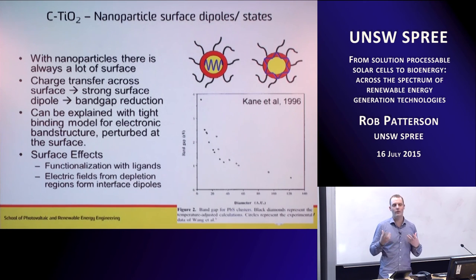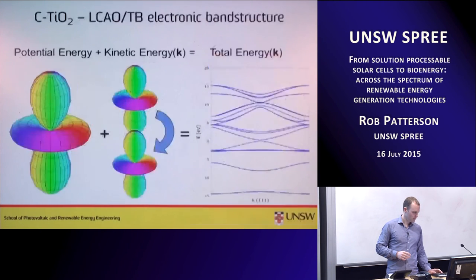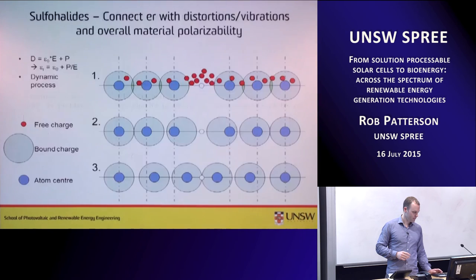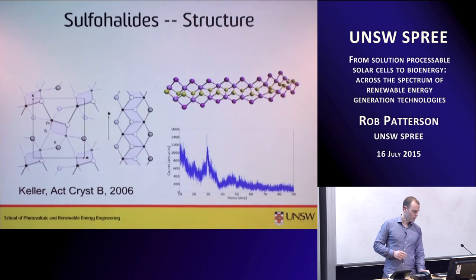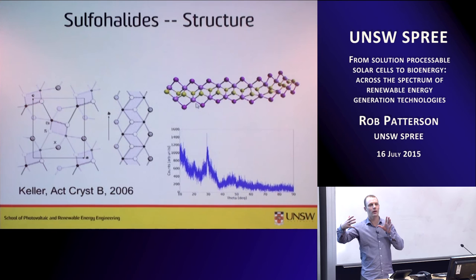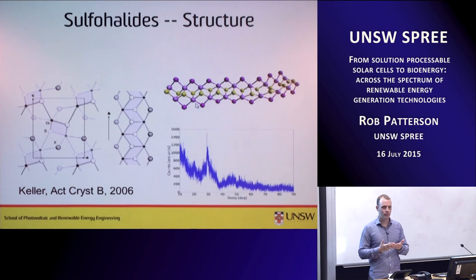The main reason, I think, is just because we have iodine on the surface. I mentioned in the talk that iodine is very sticky. So you have this nanowire. These purple ions are basically what is exposed, and that iodine is very polarizable. It can stick to itself. So in solution, I've tried to screen them using electrolytes. I've tried to add water because it's highly polar. And the net result is that the nanowires stay suspended for longer, but eventually they go and find each other.